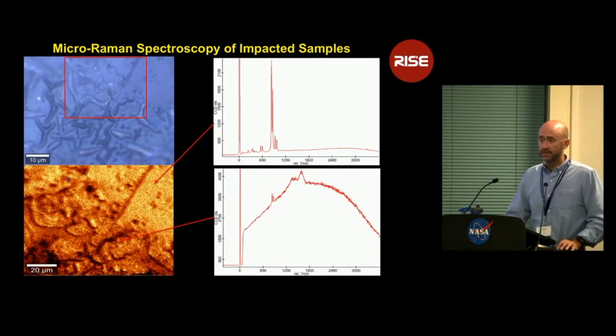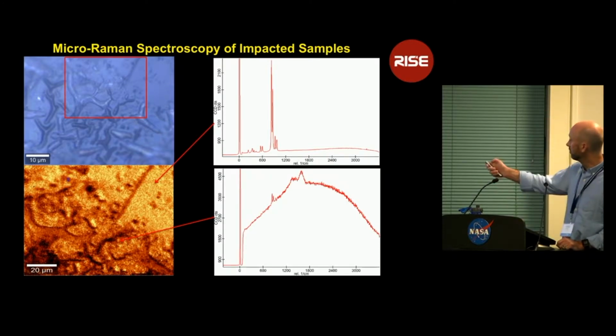We can go down in spatial scale. This is data that was collected by my graduate student, Jordan Young. So here we're looking at micro Raman data, and these are at spatial scales of roughly 500 nanometers per pixel. We see a beautiful olivine Raman spectrum up top from this relatively undamaged area. When we go down and look at a more damaged area, we see the olivine peaks are still there, but